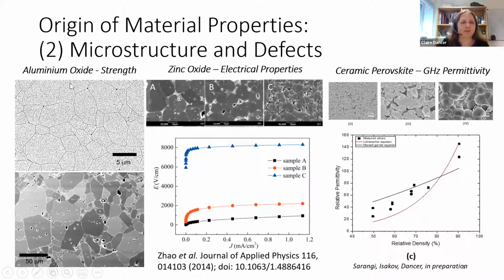So what are these materials? Well, the top one was made from super expensive Japanese super high purity aluminium oxide powder, and made very, very carefully. The bottom one is what happens when you're bored in the lab and decide you want to look at a piece of a broken furnace tube under the microscope, and you polish it up and have a look at it. So this is a piece of furnace tube that was broken, and it shows you the defect structure within it.